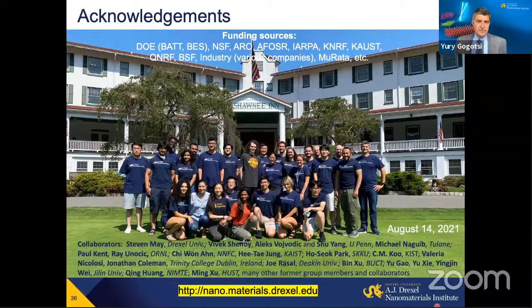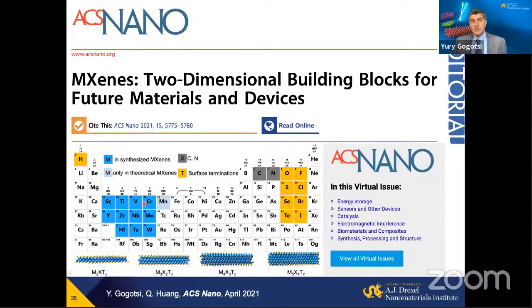Basically, if you look at the materials that I showed to you, they are carbides and nitrides of transition metals. And many, especially say molybdenum and tungsten carbides, have been known for a long time to be efficient catalysts, photocatalysts, and electrocatalysts. I'm not an expert in catalysis. In my group, we work, again in collaboration with Alex Voivodich, who does DFT prediction at Penn, and also colleagues at other universities in the US and abroad, on, for example, the hydrogen evolution reaction. What is interesting in MXene, for example Mo2C, is that the entire surface is catalytically active, unlike in dichalcogenides, where the sulfur-terminated surface is passive and only edges provide catalytic properties. So this is one of the interesting applications.